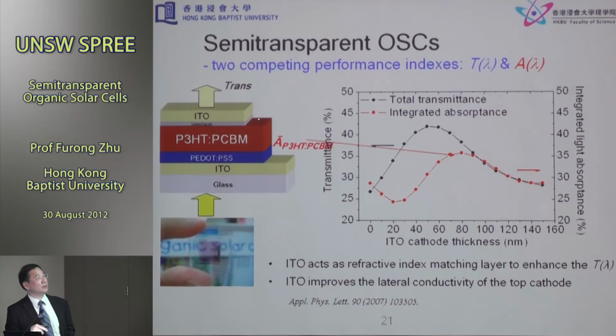For semi-transparent solar cells, the idea is the same. We want this to be as transparent as possible, but at the same time also absorb the maximum incoming light. Therefore, I have a system that transmits light and also generates electricity from the light. So essentially, we're talking about two competing performance indexes for semi-transparent solar cells. The first thing we look at, again, is the absorbance of the blend layer in this system, and we scan the layer thicknesses, looking at the deposited ITO.